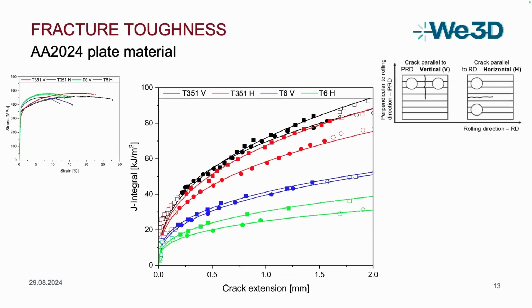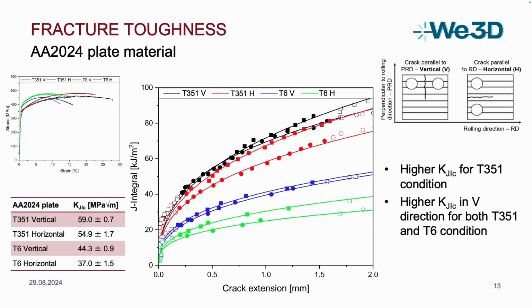Now we go to the fracture toughness of the 2024 plate material. We have here all the resistance curves in this diagram, and we have the T351 resistance curves in the upper region and the T6 R curves in the lower region. That correlates great with the tensile tests of this material because the fracture strain is also reduced. And furthermore, we can see that in the vertical orientations, we have a higher fracture toughness for both conditions than in the horizontal orientation.